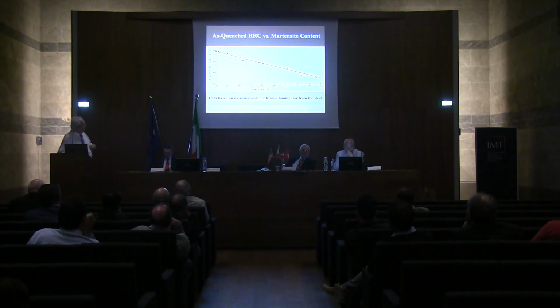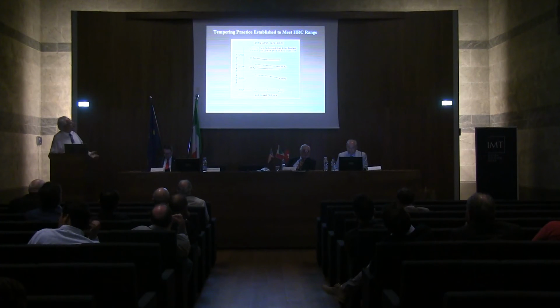And these are data based on measurements made on a Jominy bar from the steel, percent martensite versus as-quenched hardness. And you can see when we're 100% martensite, we're up around 60 Rockwell C. And as we drop in martensite, the hardness goes down. And this is tempering practice established to meet the hardness range. 32 to 36 is the hardness range.